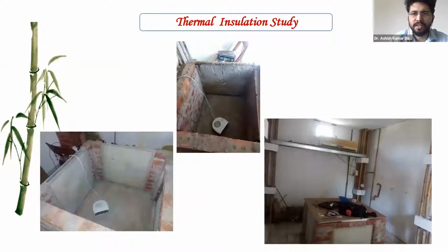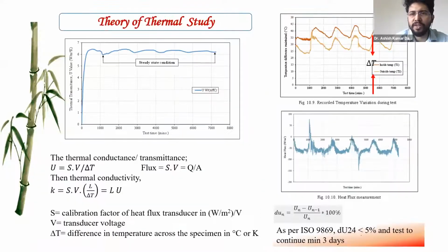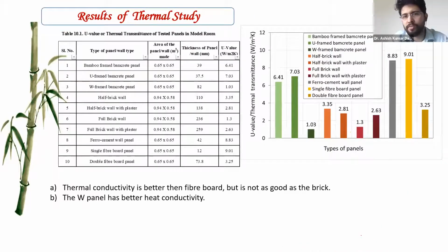And this is the result that we got, the flux variation with day and time. The test was run for 5 days, 6 days, 7 days like that, till we get the standard variation less than 5%. And these are the different U values, that is the watt per meter square Kelvin, the thermal transmittance value.